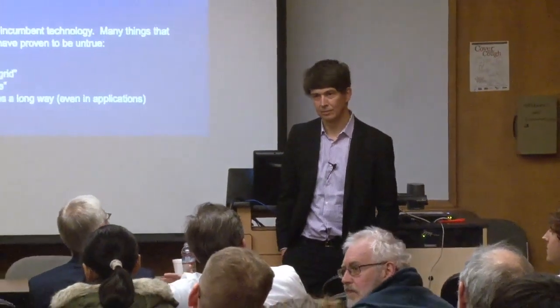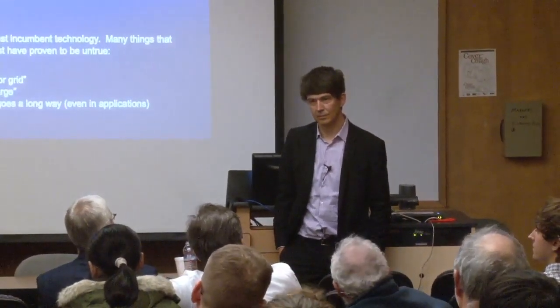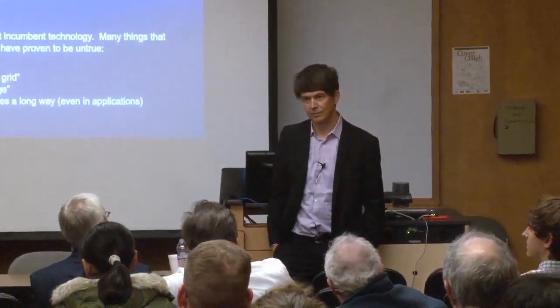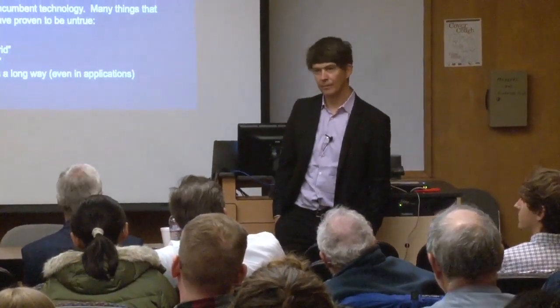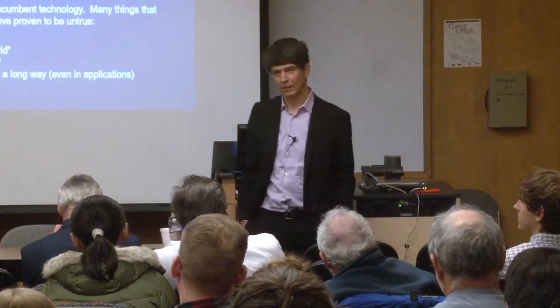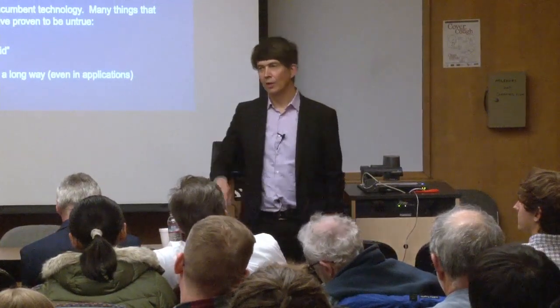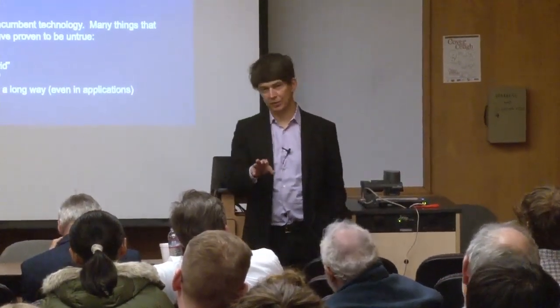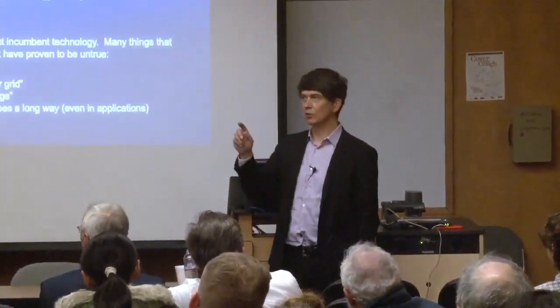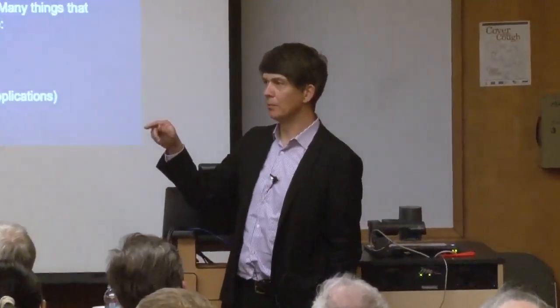So I'm curious about this percolation threshold with a lithium. It seems to me to percolate at 10%, you have to have some ordering force. You wouldn't get random population. What is it that causes that percolation threshold to be so low? Oh, so it's actually 10% lithium excess. So that means in the stoichiometry, it's 1.1 lithium, 0.9 metal. So it's actually 55%. Sorry, I didn't say it.